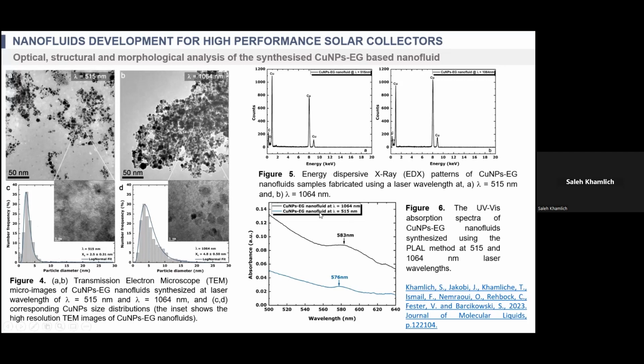As you can see from the UV-Vis spectra of these materials produced, this is copper in ethylene glycol, of course. The ones produced at 515 nanometer show this trend, or this curve. The one at 1064 shows this, and this is the surface plasmon resonance band of the copper. It shows clearly that we produced copper. But this one looks small, that's the intensity of the absorbance. This one is high.